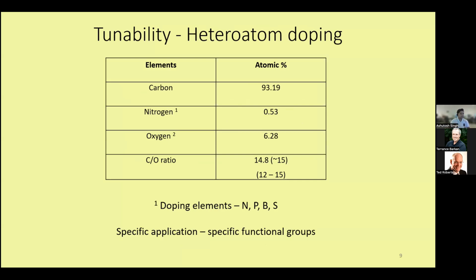Now, coming back to our tunability or flexibility in the operating conditions. If we slightly change our parameters in the operating conditions, or if we change the chemistry, we are able to dope a separate heteroatom into the graphene structure. Allow me to explain. We have carbon, obviously, because of the graphene, and oxygen, because of the functionalization. But in addition, we sometimes have nitrogen doped into the structure, and we can change it depending on the chemistry of the solution. You might ask what this really adds. If you do a lot of electrochemistry, you would see that nitrogen in a carbon or graphene heterostructure acts as an electrocatalyst and can improve electrochemical reactions.